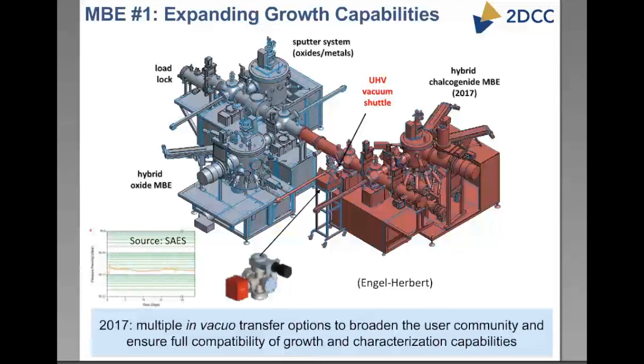One of the unique aspects of this particular MBE system that Roman is setting up is that the sources are going to be metal organic. So this is going to be hybrid chalcogenide MBE. The reason for doing that is because we want to play around with the nucleation and growth kinetics. And it turns out that our theory colleagues who use reactive force field methods have ways in which they can actually help us figure out what are the right precursors to use. They can do modeling and hopefully guide the synthesis program in a positive direction.